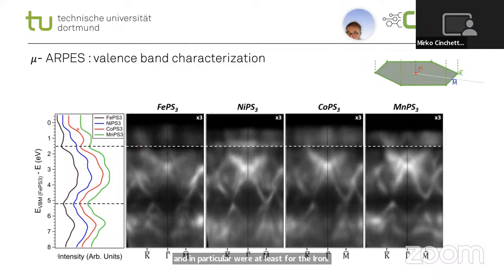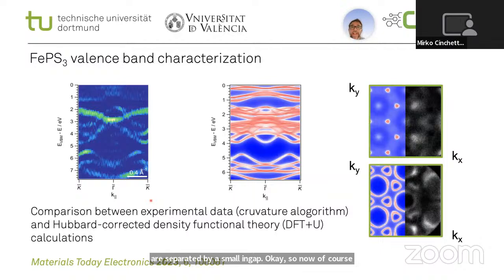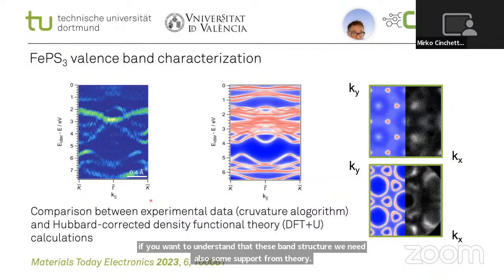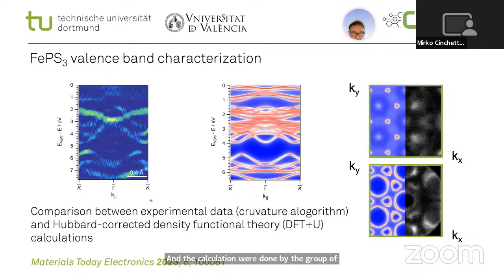We have 3 groups of bands that you can also recognize here in the angular integrated intensity. You see we have here a minimum and here another minimum. So these minima distinguish these 3 groups of bands that are separated by a small gap. Okay, so now, of course, if we want to understand this band structure, we need also some support from theory. And the calculations were done by the group of Jose Baldoví, who actually gave the seminar last week. And they used DFT plus U calculations to calculate the band structure to compare with our experiments.